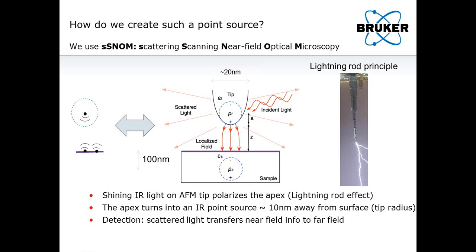The way you do that is by monitoring the scattered light of this AFM tip. The scattered light transfers the interaction of these evanescent waves with the sample into the far field. So you're transferring near field information to the far field. If the sample causes a change in the tip dipole, it will affect the overall scattered light by the entire tip.